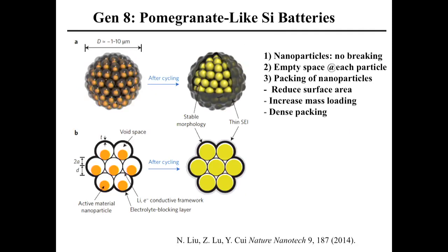What's the design principle right there? We know the volume expansion happening, it breaks. So small things don't break. Number 1, you need small guys. And then because of volume expansion, it's going to squeeze the surrounding environment. In order not to break the surrounding environment, what do we do? Leave some empty space right there. How do we do that? We take silicon nanoparticles, 80 nanometer in diameter, small enough they don't break anymore. And doing a very advanced nanomaterial synthesis, we can design empty space right there. Just fits exactly to accommodate this volume expansion, with a conducting carbon coating right there.